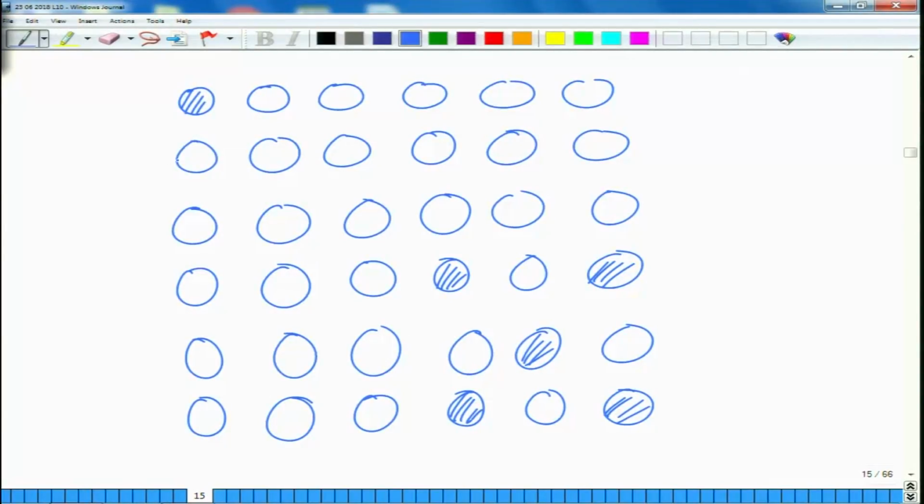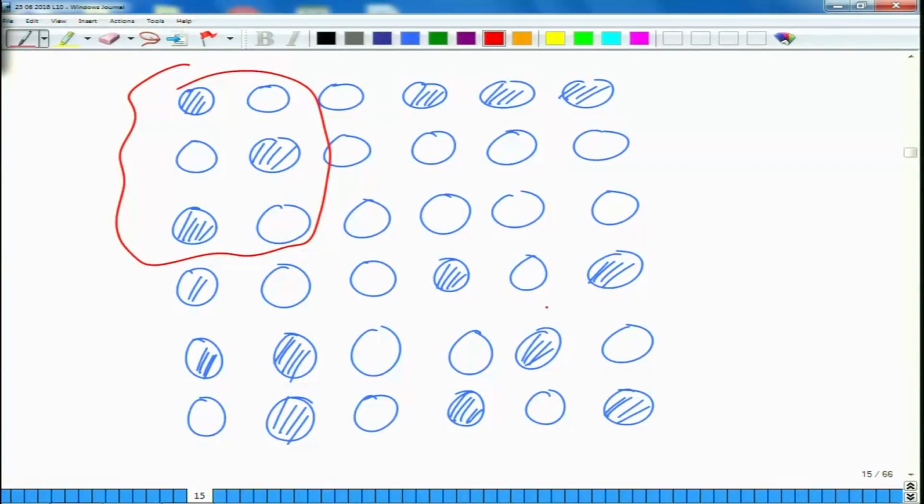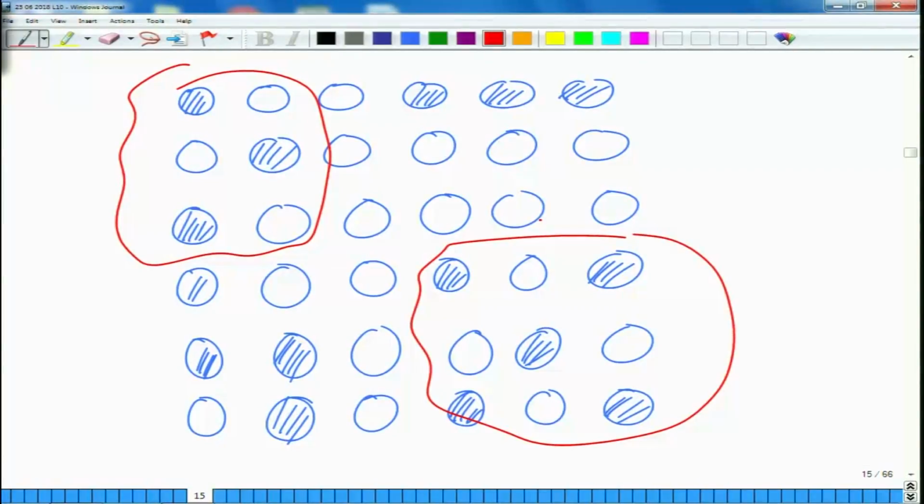Here also, let us say, you have ordering, but in other regions you have disordering. So, they do tend to form clusters. So, you can see that certain regions are ordered, certain other regions are disordered, or you can say certain regions are perfectly ordered. So, this is short range order, but other regions are random, so clustered there. So, this is an example of partial or short range ordering.